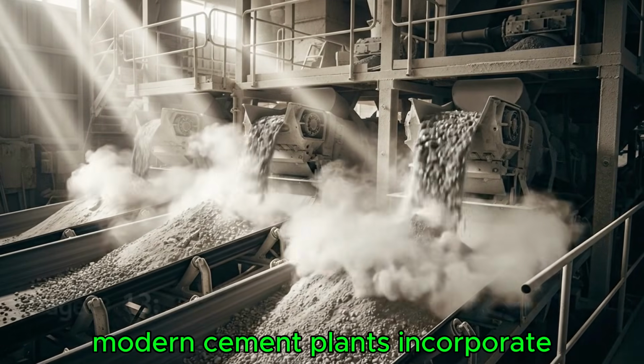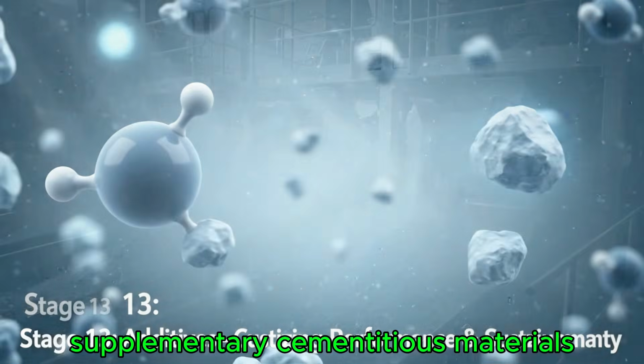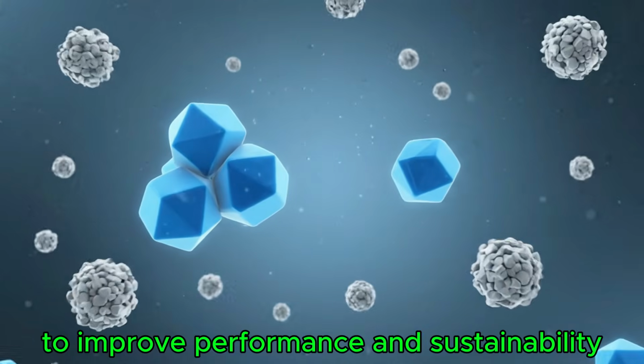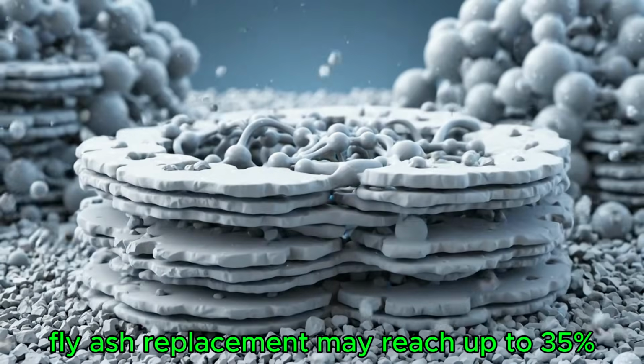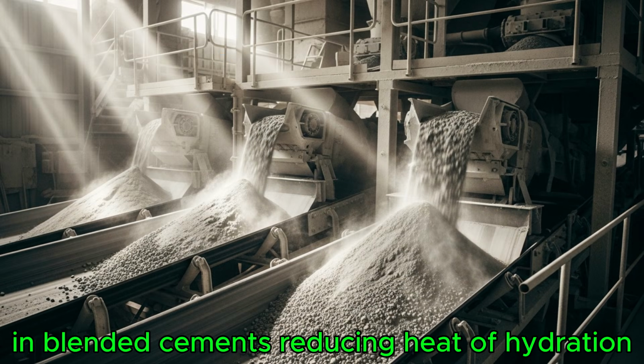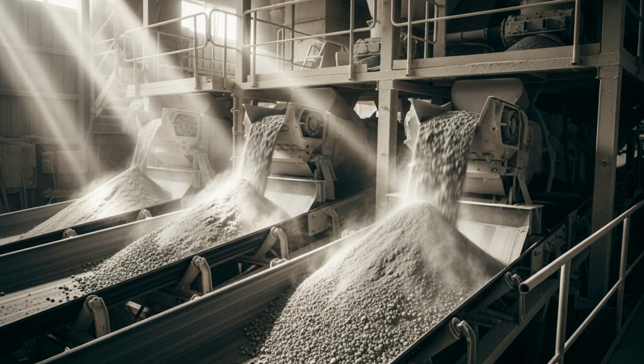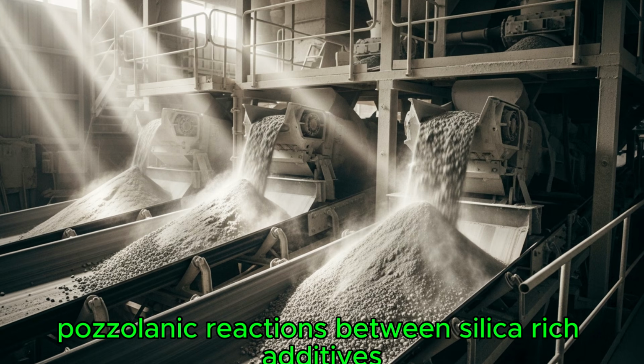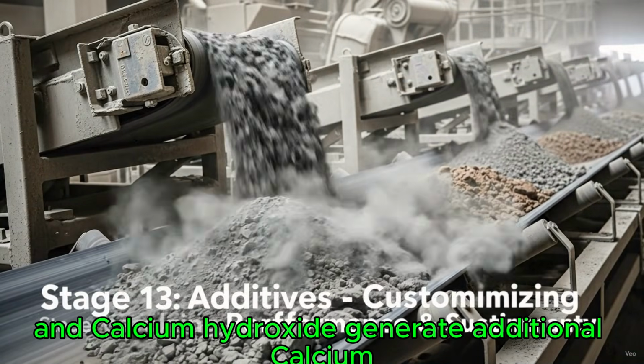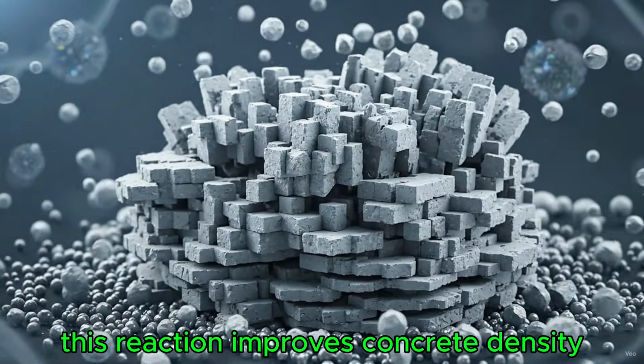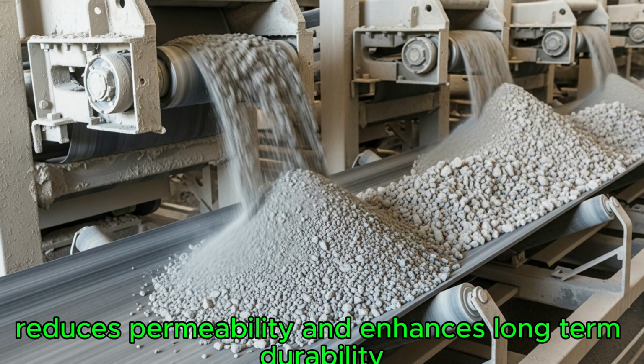Modern cement plants incorporate supplementary cementitious materials such as fly ash, slag, silica fume, and limestone fillers to improve performance and sustainability. Fly ash replacement may reach up to 35% in blended cements, reducing heat of hydration and improving sulfate resistance. Pozzolanic reactions between silica-rich additives and calcium hydroxide generate additional calcium silicate hydrate gel. This reaction improves concrete density, reduces permeability, and enhances long-term durability.